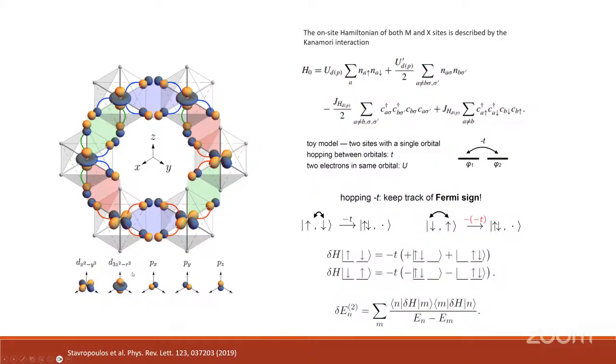So I put an example here, like the spin momentum of each nickel d orbital. They could be different along the different directions. This is because, as I mentioned, the spin interaction between the nearest neighbor sites is mediated through the ligand, the transition metal-ligand-transition metal hopping. However, the plane of each hopping path is perpendicular along three different directions.